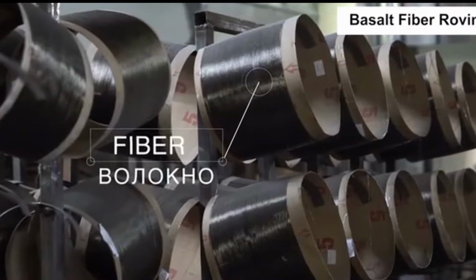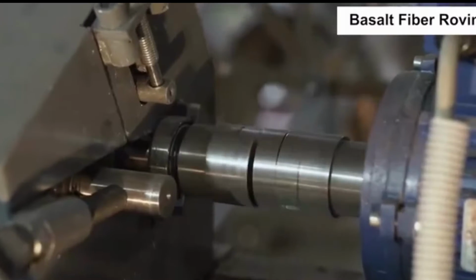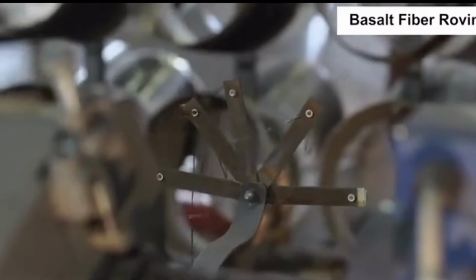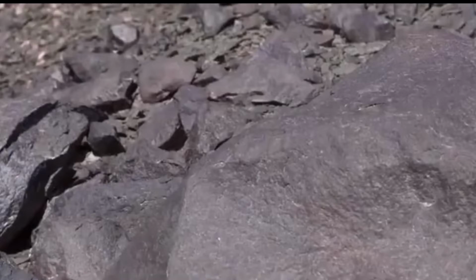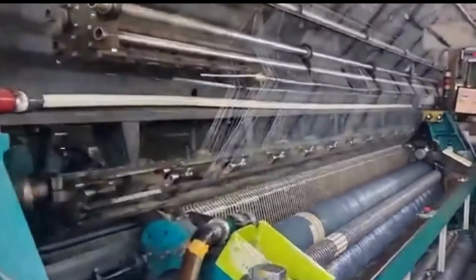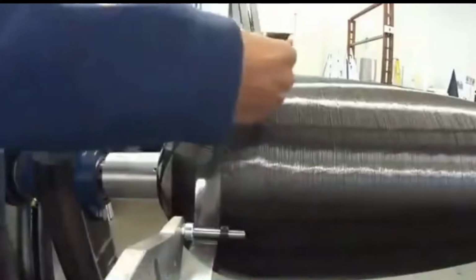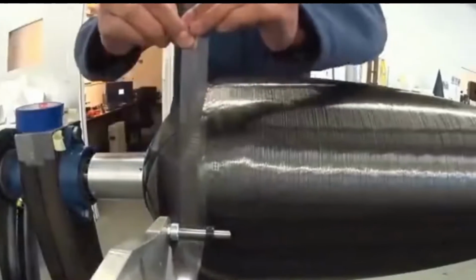2. Lower thermal conductivity. The thermal conductivity coefficient of CBF ranges from 0.031 W/mK to 0.038 W/mK, which is lower than that of aramid fiber, aluminum silicate fiber, alkali-free glass fiber, rock wool, silicon fiber, carbon fiber, and stainless steel.